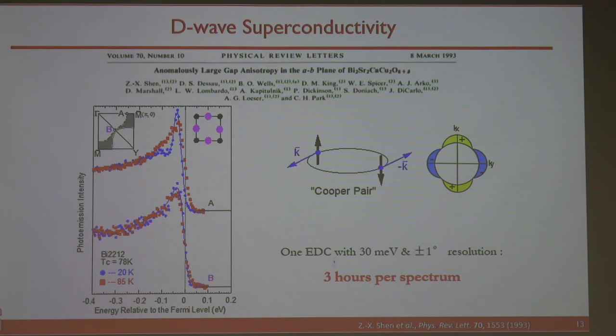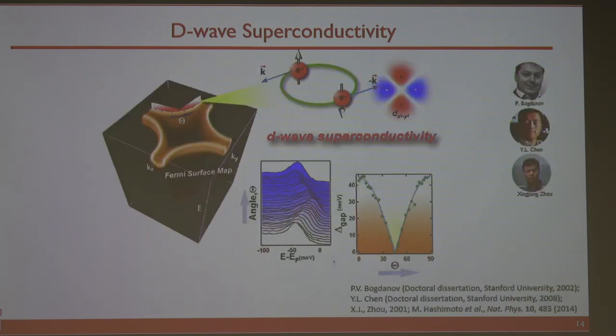We have, but from the ARPES point of view, you can see the work here that you can now measure the spectrum around the entire Fermi surface. You can see it shifts. Just plotting the energy position of the shift as a function of angle, you see the data points, and the blue is the d-wave fit. Okay, it's a pretty good fit.